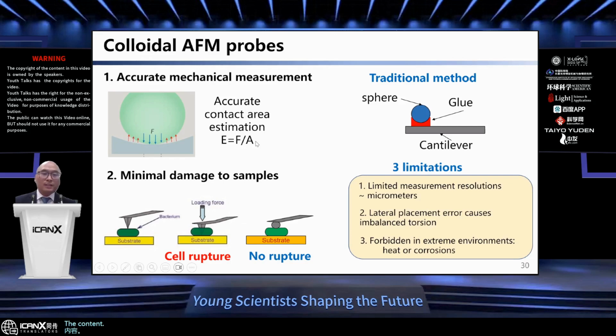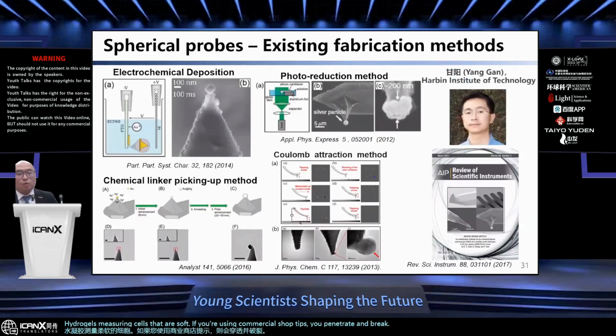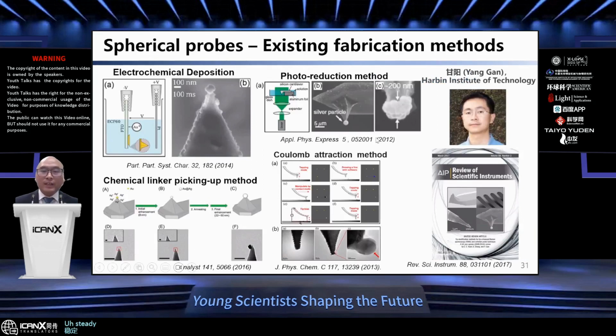Once you can predict the contact area, you know the force, you can get the modulus or the elastic property of the sample. Also, a spherical probe is great for measuring hydrogels and soft cells. If you use commercial sharp tips, you penetrate and break the sample. Professor Yang Gan from Harbin Institute of Technology wrote a review paper stating the great need for making these microsphere probes into nanospherical probes because of the limited resolution.